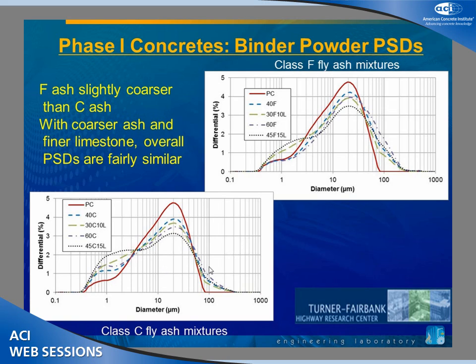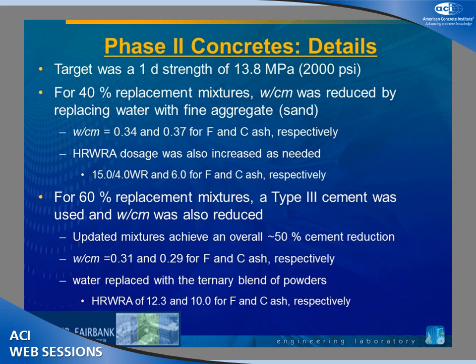We're still covering basically the same range, and there are certainly some differences in terms of the fines in here with the C-ash and the limestone, but it's not a dramatic change, and that might be one of the reasons we don't see dramatic changes in terms of slump. We can actually cut back on the water reducers a little bit because of the dilution, taking some cement particles out of the system, and also perhaps the spherical nature of the fly ash.